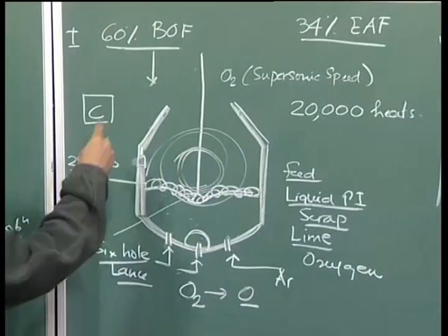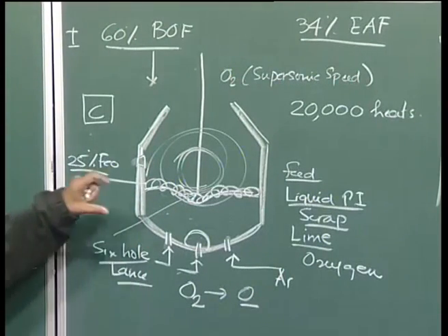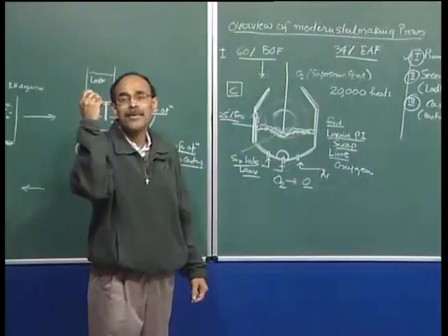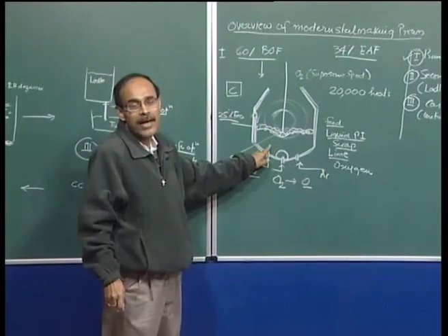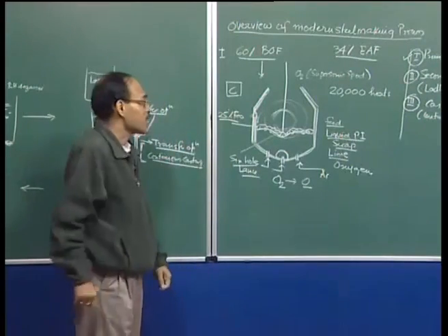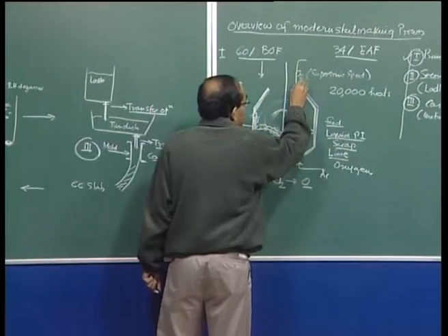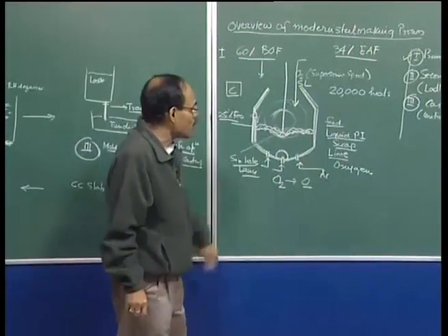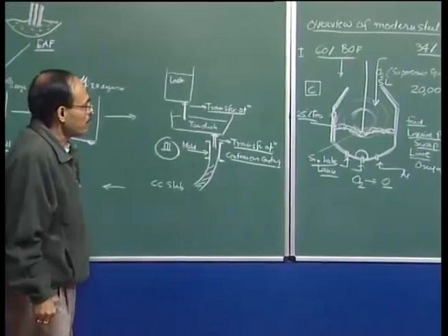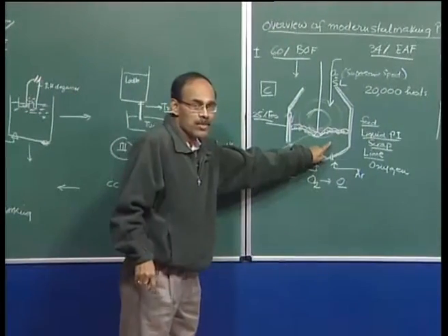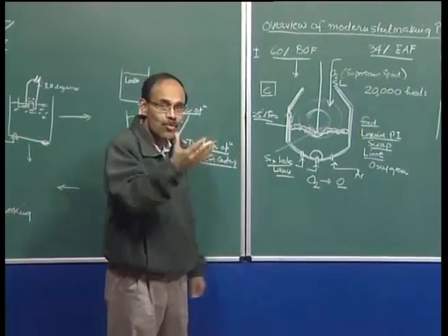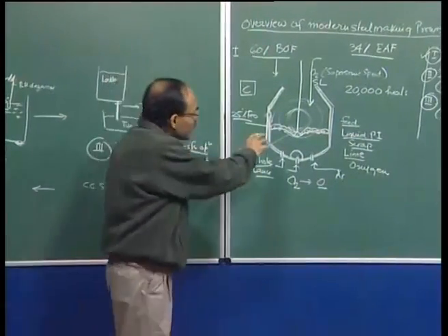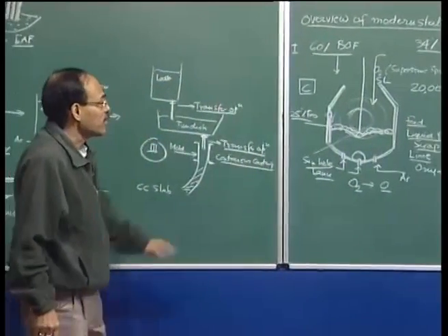And after steel making blowing, we initially introduce oxygen, and then after some time, we take samples to find out how much carbon is there, and then control the end blow period. Based on that sample analysis, we also have a sublance. The sublance is immersed into the molten metal, and a sublance sample is collected, and we know how much heat is there, and what is the level of carbon present. Based on that, we fine tune the final stages of blow, introduce the requisite amount of oxygen,